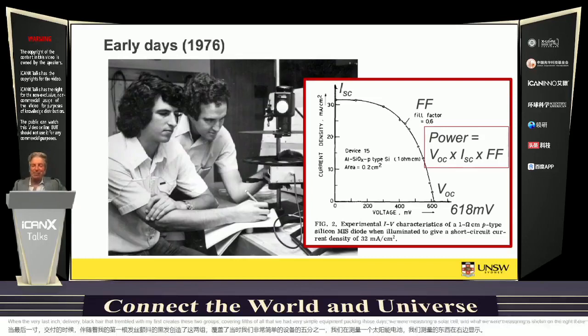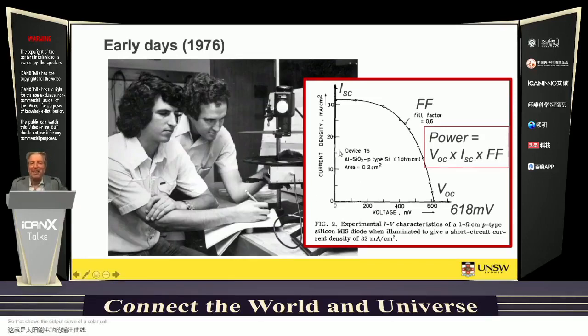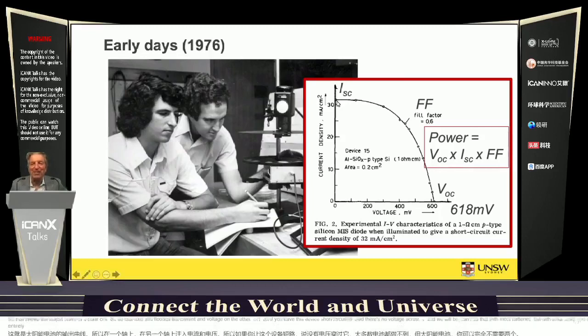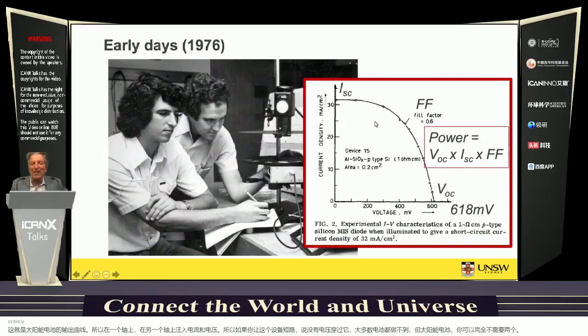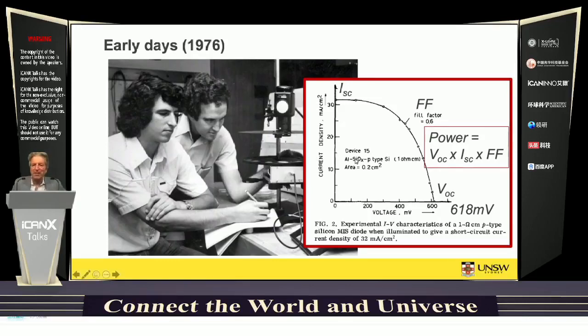So that shows the output curve of a solar cell. So on one axis is plotted the current and voltage on the other. So if you have this device short-circuited, so there's no voltage across it, you can't do that with most batteries, but with solar cells you can, without doing them any damage in most situations. You get the short-circuit current. And if you open-circuit it, so there's no current flowing from it, you get the open-circuit voltage. So there's zero power at both those bias points because the power is the product of current and voltage, and one of them is zero in both cases. So the maximum power occurs as you move along this curve towards the maximum power point.